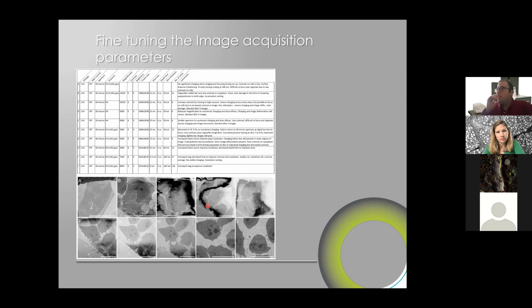Before going into that part, that's when we decided to say, okay, we have a product, we need to upscale it, because having it in my lab is one thing, but as a company we need to be able to diffuse it. And so with our chemist, we decided to make a big batch, and then we had to fine-tune that, because actually the big batches that we could order from the big company to synthesize the polymer were not of the same quality as the one we used for the testing. And so basically we had to do this exact same procedure again.